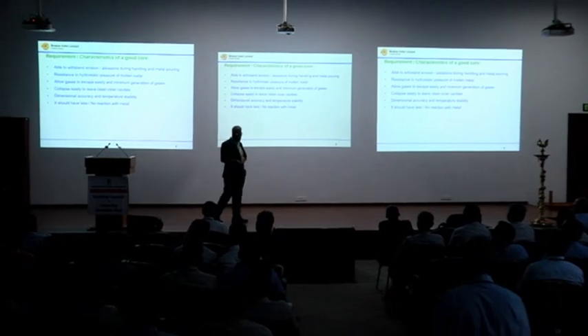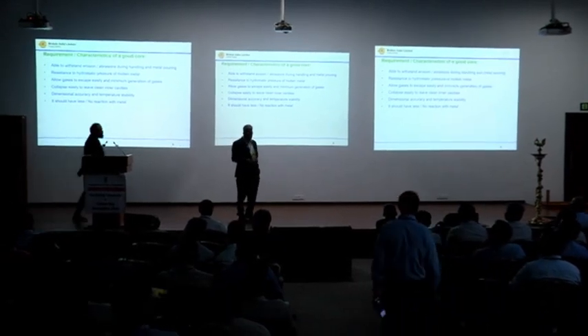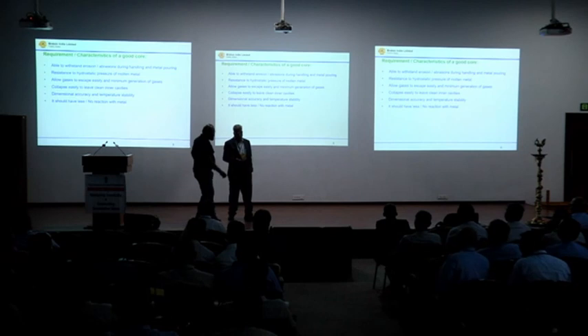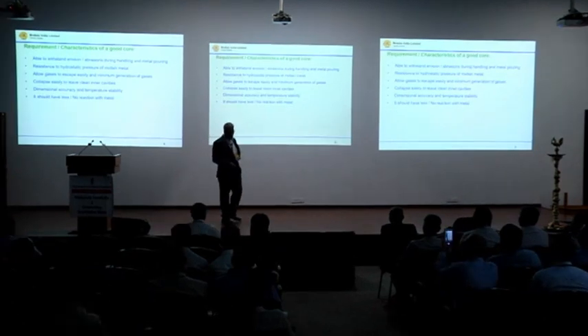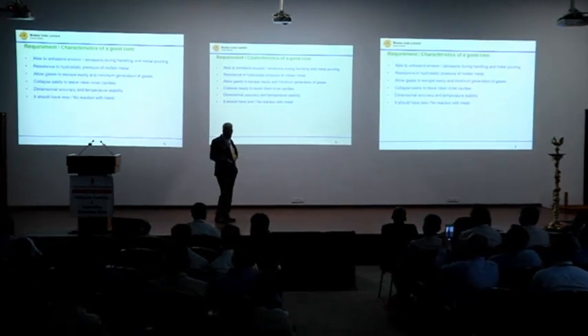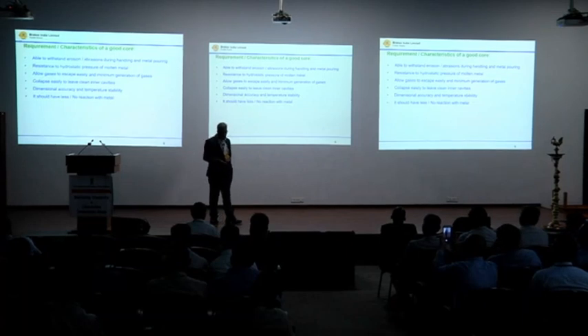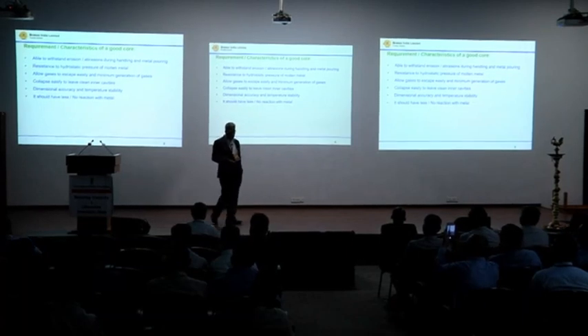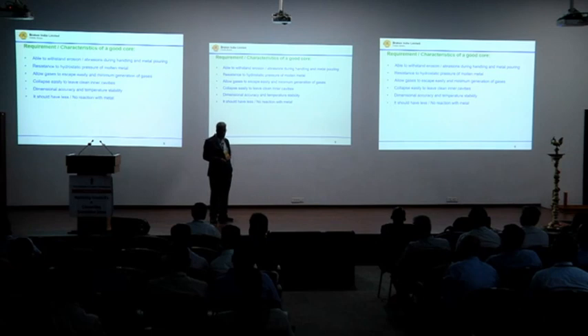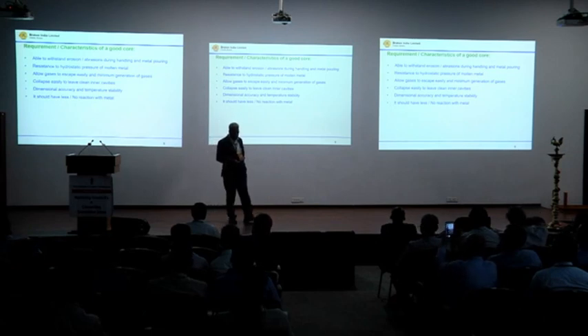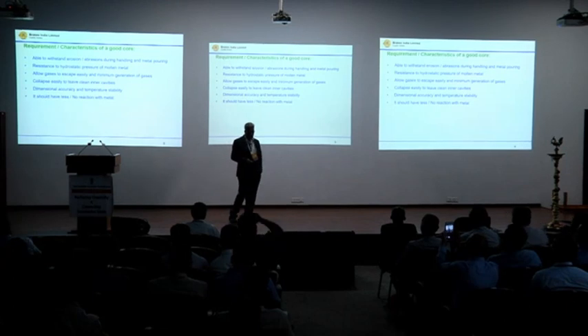So the requirement of a good core: able to withstand erosion, abrasion during handling, and metal penetration, hydrostatic pressure of the molten metal, allow gases to escape easily with minimum generation of gases, collapse easily to leave clean inner cavities, dimensional accuracy and temperature stability. You should have less or no reaction with the metal.